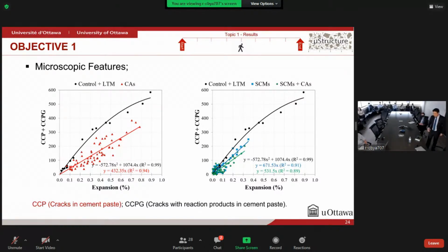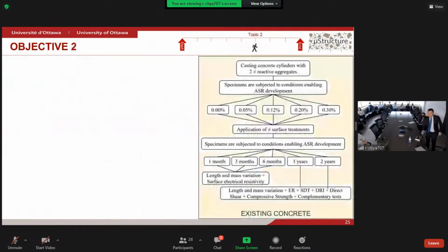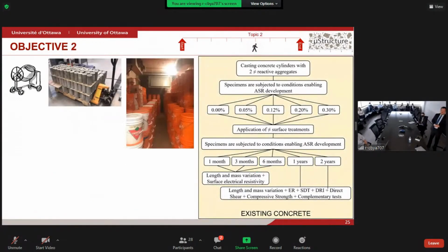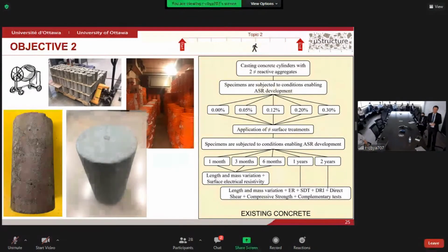So now that we know that it works for new concrete, can we use this technology as a surface treatment of ASR affected concrete as a feasible solution to mitigate further reaction and ASR induced development in concrete? So for that, we cast different concrete cylinders with the same two reactive aggregates as before, but now only using Portland cement as a binder material.